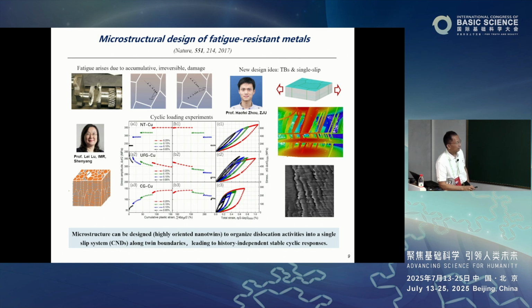However, we found it is indeed possible to design a microstructure to avoid this. For example, I have a little simulation here. This shows that instead of random boundaries, we can design parallel boundaries, like the so-called twin boundary in materials science, as this structure shows. Then we could organize the dislocations so they become highly organized.